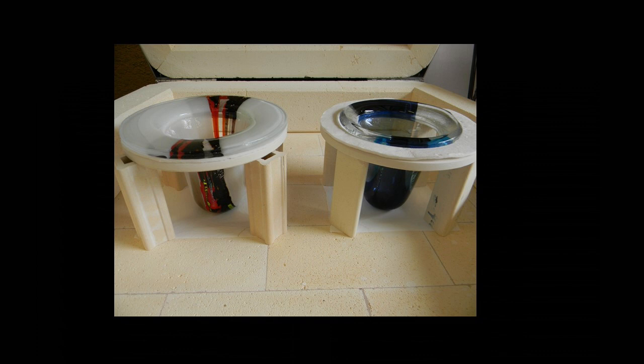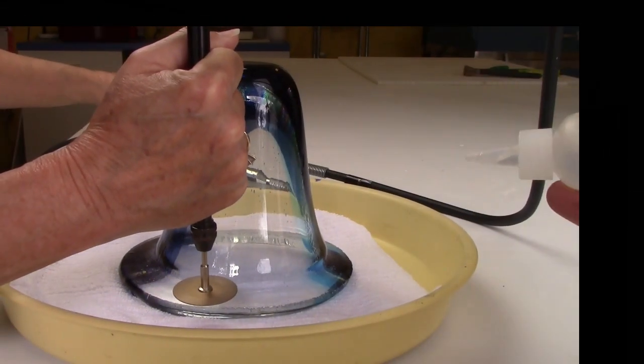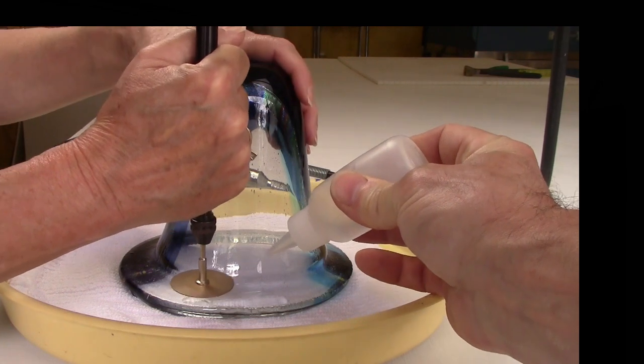While these pieces of glass were dropping through the mold, I peeked inside the kiln about every 15 minutes until the glass just kissed the bottom of the kiln, and that's when I turned the kiln off and started the annealing process. You can leave the rim on the vase if you want to.